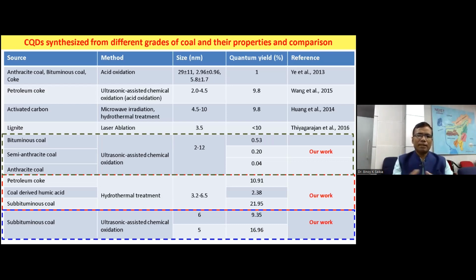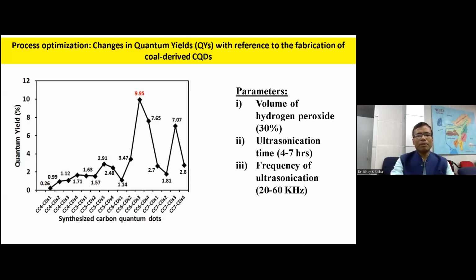We have not applied any inorganic acid. So our quantum yield, you can see, is around 21.95%, the maximum with the subbituminous coal of Northeast India. Then we optimized and found that, out of the several coal samples with different properties or chemical constituents, particularly the carbon and nitrogen, a maximum of 10% quantum yield is always possible. It is possible with different types of carbon-containing coal.